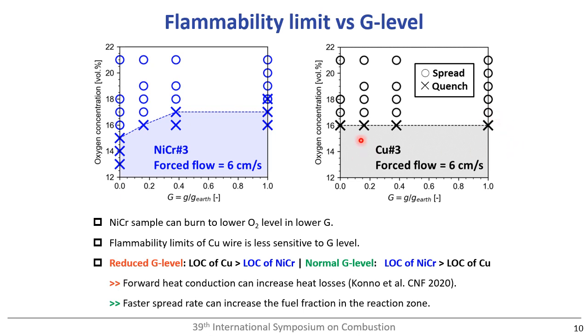Another interesting point is the flammability limit, so the limiting oxygen concentration of the copper sample shows a larger value than the nichrome wire under low gravity conditions. But in higher gravity conditions, the limiting oxygen concentration of the copper wire shows a lower value. That means in low gravity conditions, copper wire suppresses the insulation flammability, but in higher gravity conditions, copper wire enhances the flammability of insulation from the viewpoint of flammability limit.